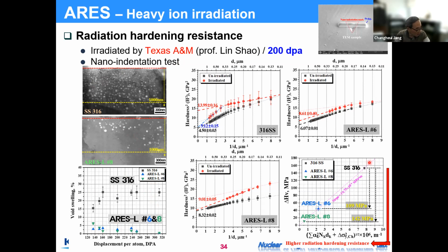Also, the degree of embrittlement is significantly reduced from conventional 316, that is 150. So we have roughly less than 50. So this one is also a significant decrease in the embrittlement.